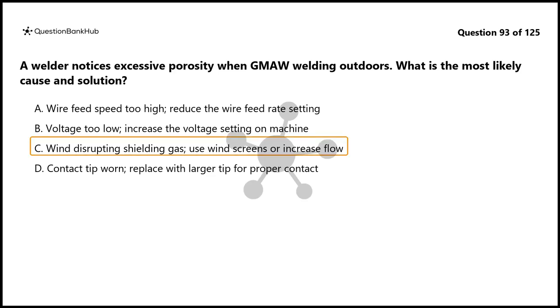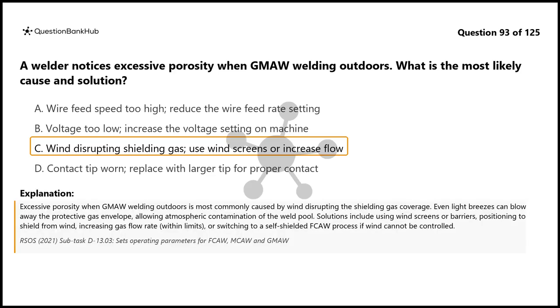The correct answer is C. Wind disrupting shielding gas, use wind screens or increase flow. Excessive porosity when GMAW welding outdoors is most commonly caused by wind disrupting the shielding gas coverage. Even light breezes can blow away the protective gas envelope, allowing atmospheric contamination of the weld pool. Solutions include using wind screens or barriers, positioning to shield from wind, increasing gas flow rate, within limits, or switching to a self-shielded FCAW process if wind cannot be controlled.